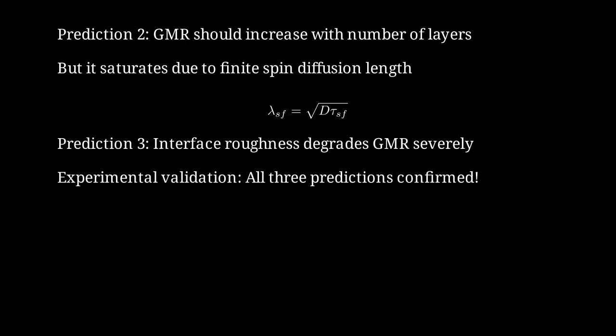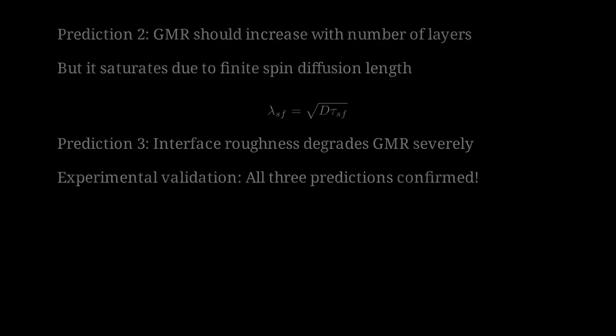Prediction 3. Interface roughness should degrade GMR severely. Even 1 or 2 monolayers of roughness can scatter electrons and flip spins, reducing the effect. Experimentally, all 3 predictions have been beautifully confirmed. By systematically varying layer thicknesses, number of repeats, and growth conditions to control roughness, researchers have validated the spin transport model in exquisite detail. Let's look at a specific example, iron-chromium multilayers, which were among the first systems to show